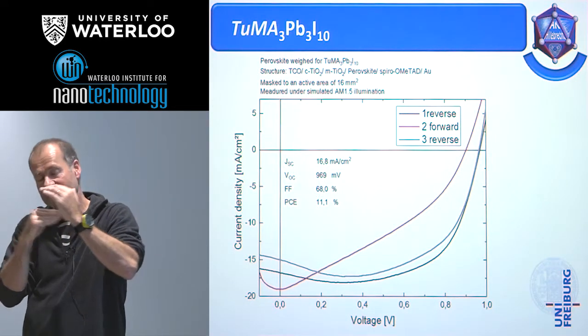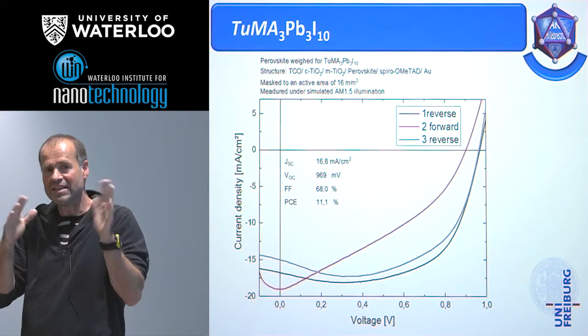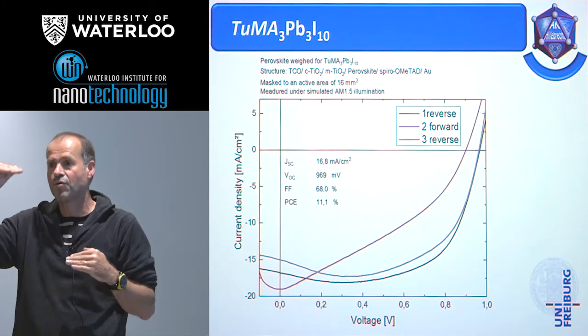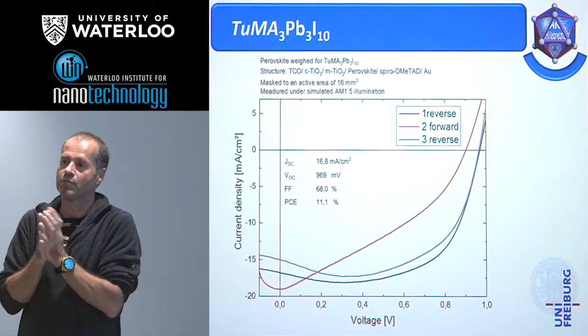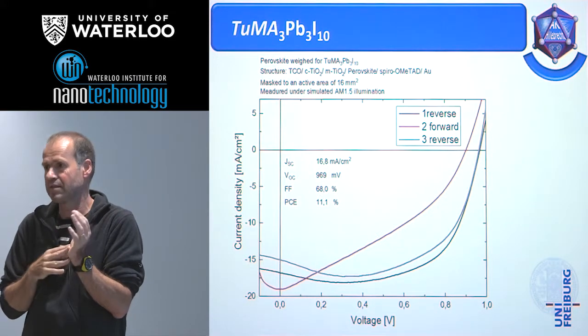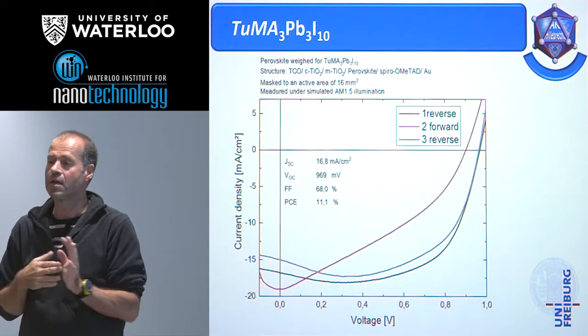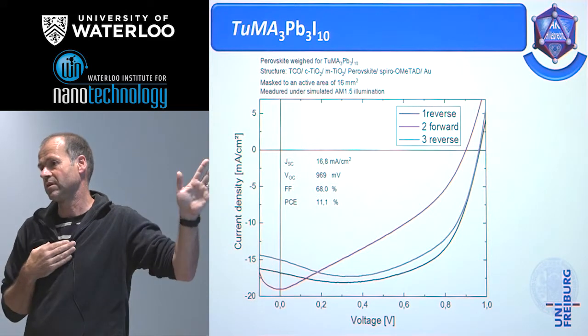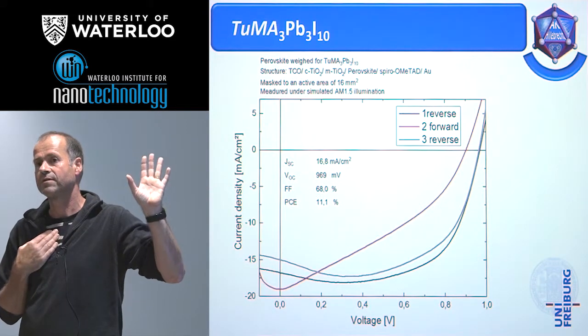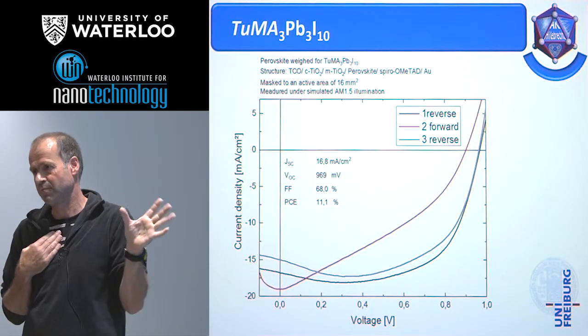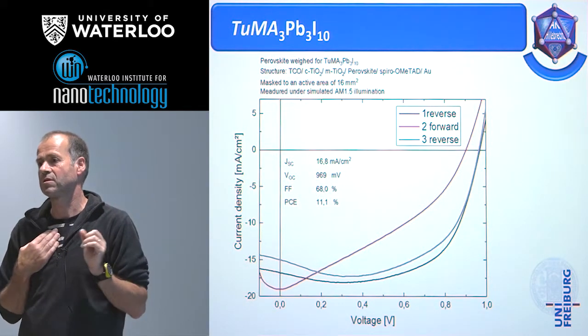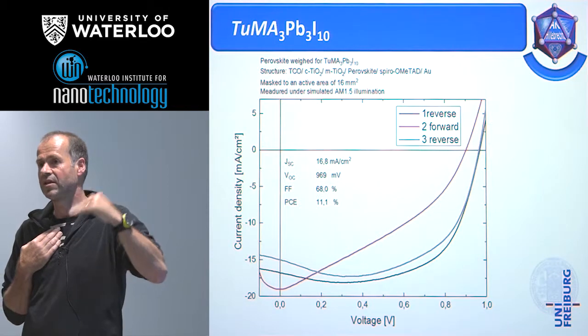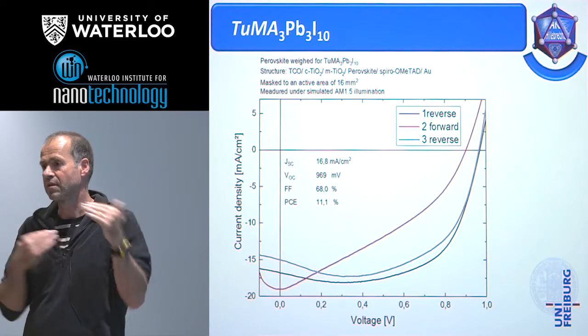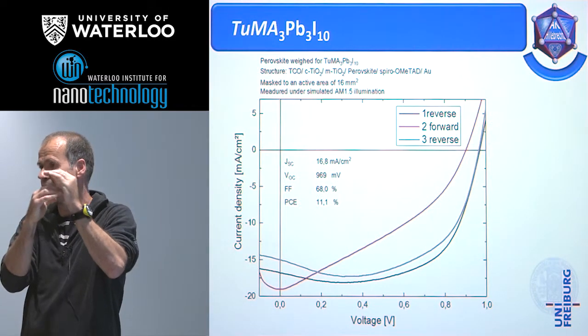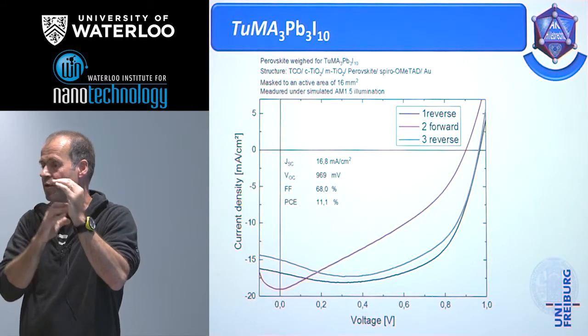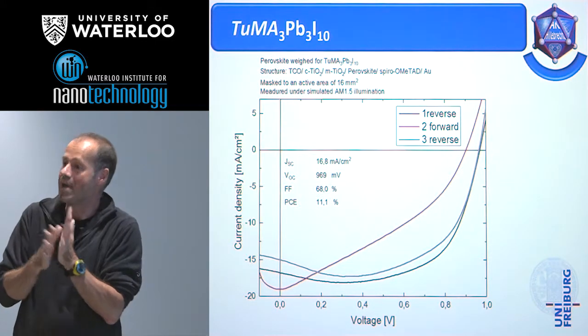And I guess you have something quite close to a three-dimensional perovskite. There's some work of Kanatzidis in this field, and we are very similar with these things that we do. And he said he arrives at efficiencies around 15% with his two-dimensional systems. But these layers that he has contain 5 layers within the lead iodide part. So it's not yet understood why.